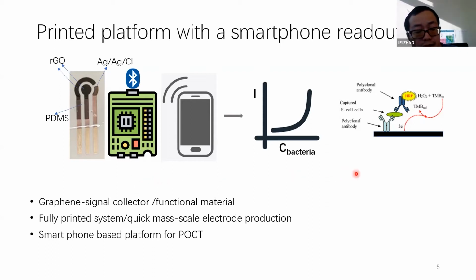For the sensor fabrication, it's a typical sandwich structure. First, we immobilize the capture antibody, which will recognize the bacteria; we used E. coli as a sample example. After this, we add an HRP-labeled antibody. This HRP will catalyze the reaction between hydrogen peroxide and TMB. After applying a potential, we can record the current signal. Then this current signal can be related to the bacterial concentration.